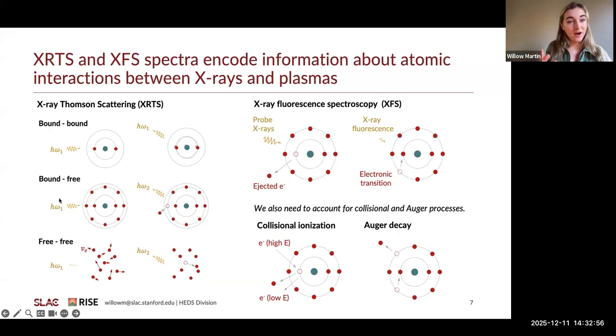And that's really where we get our strongest constraint on electron temperature because we're directly probing the distribution function of these electrons. In principle, the distribution function will depend on both the electron temperature, characterizing the velocity, or if you're in a very degenerate state, it will also depend sensitively on the mass. And usually when we're operating in a warm, dense matter regime, we're somewhere messily in between the two. So that's where we get our primary constraint on electron temperature via X-ray Thomson scattering, in at least the non-collective regime, and I'll focus on that for now.